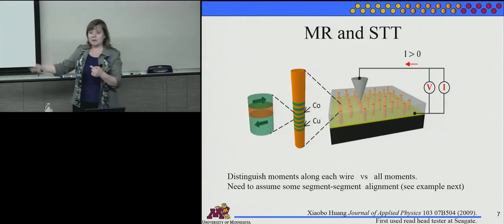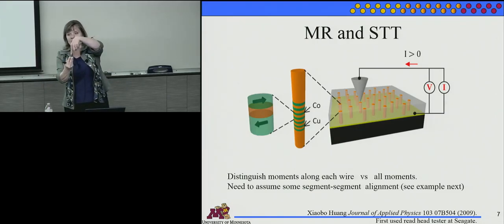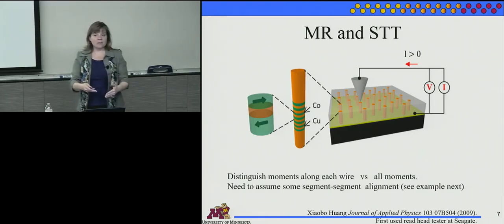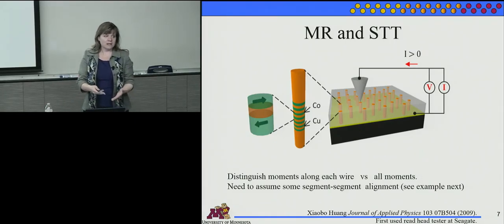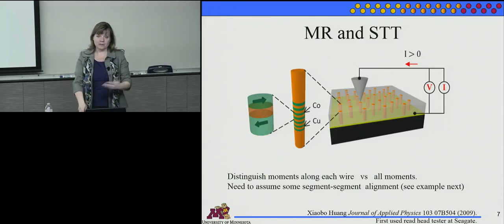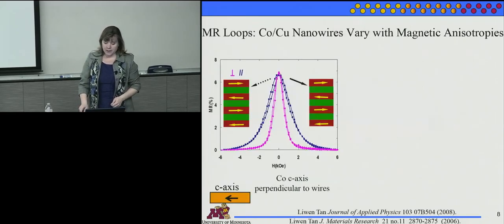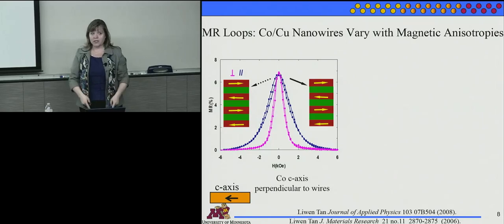So what happens is you might come down with your tip, and as you put a little pressure on it, you pick up 2 or 3, depending on the rounding. And then you'll have jumps in your resistivity, literally because you're just picking up another wire, and you'll have parallel resistors. But meanwhile, you're sensitive to the direction along the wire.